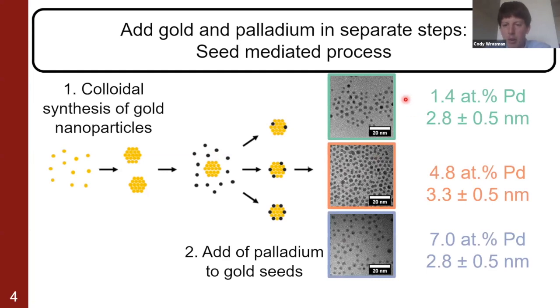And I don't need to get into the details here, but we were able to get amounts of palladium as low as 1 atomic percent. So 1 in every 100 atoms in these nanoparticles was palladium, and the other 99 were gold. So that gave us hope that we were getting those very, very small amounts of palladium into these gold nanoparticles.